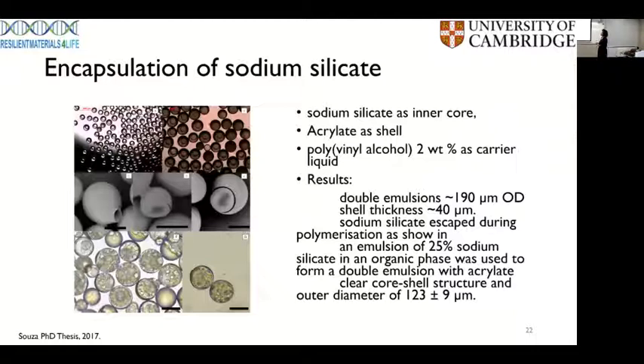Interestingly, one of the things that I did during my PhD was to encapsulate sodium silicate. In this case, what I did on a Wednesday afternoon was to just try to encapsulate the pure sodium silicate with the acrylate shell, using that laminar property of microfluidics that I was talking about, so that the two chemicals are not going to mix directly. This is important because sodium silicate is very alkaline and very reactive, so you want a system that is stable enough for encapsulating it. So these are the double emulsions, and those are the capsules observed under SEM.